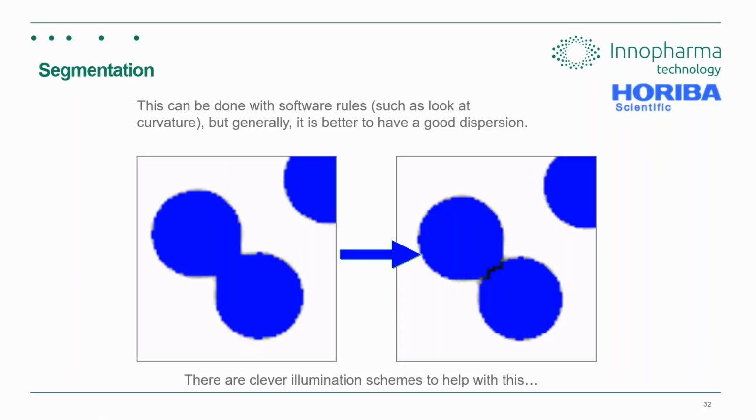If we look at segmentation, before, for the dispersion example, we saw some particles touching. If we're looking at, again, a binary image here, just two-tone, and the particles are touching, our image analysis system on the left might detect this as one particle because there is no defined boundary between the two of them. So this is where you would want to come along with some of your filters. Again, Watershed was a good one for separating particles like this that I've seen in the past. And then you can define two particles. So you can do a lot of good processing for segmentation with your image analysis. Again, the flexibility is there to do that.